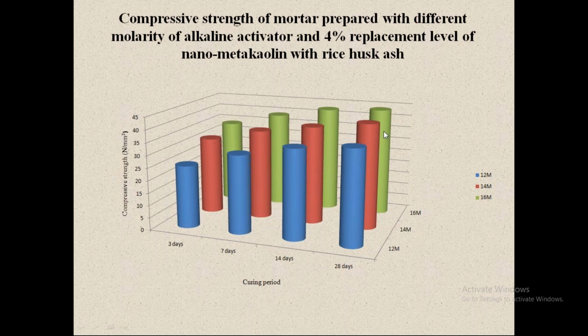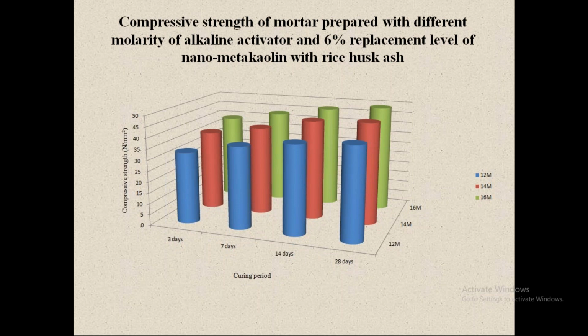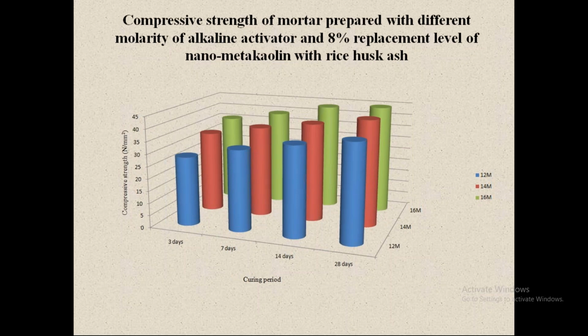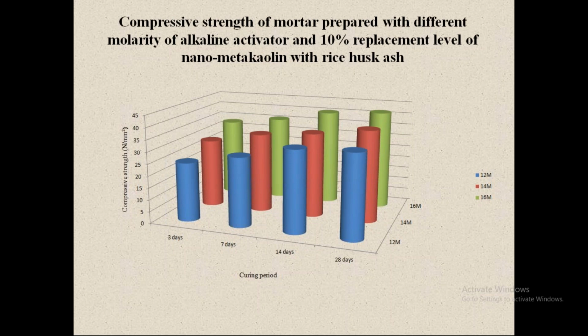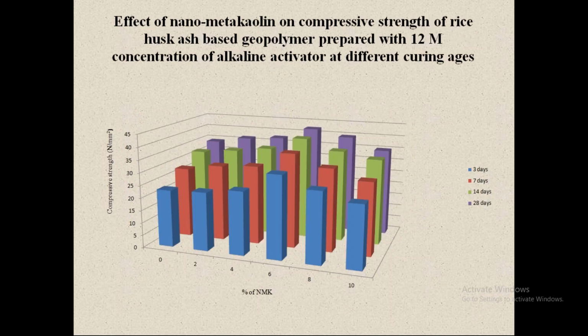And when we replaced it with 4%, again there was an increase. The increase was 12.33% for 14M and 16.61% for 16M. Again, for 16 molarity a similar trend was observed. So there was an increase in compressive strength with increase in molar concentration of the alkaline activator. Basically, this increase is attributed to the high dissolution of rice husk ash, which is promoted by higher concentration of sodium hydroxide. When we are activating the waste, we are actually improving its properties. Similarly, it was with 8, 10, and with 12 molarity.